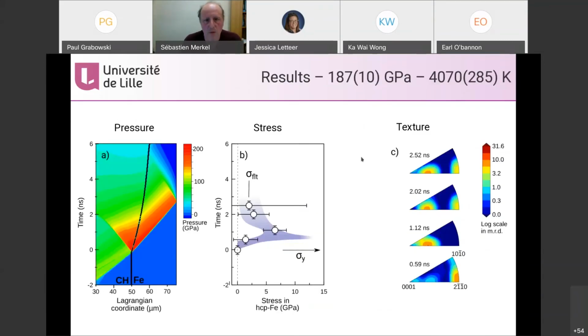So here are the results for HCP iron. On the left, you have a simulation with the pressure as a function of time. The time is vertical in this figure, and the sample of iron is here. Color is pressure up to 2 megabar. I put time equals 0 when we see HCP.